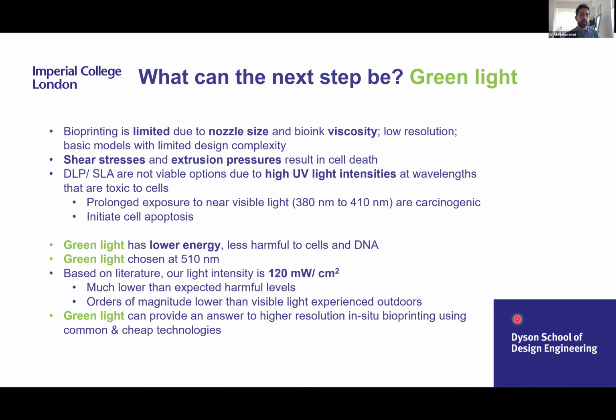And based on literature, our intensity has been set in our work to 120 milliwatts per centimeter squared, much lower than expected harmful levels. So these orders of magnitude are also lower than the visible light experienced outdoors when you're walking in the park or when you're out swimming. And that is also important as algae is always out exposed to light. So green light can provide an answer to higher resolution in-situ printing using common and cheap technologies,